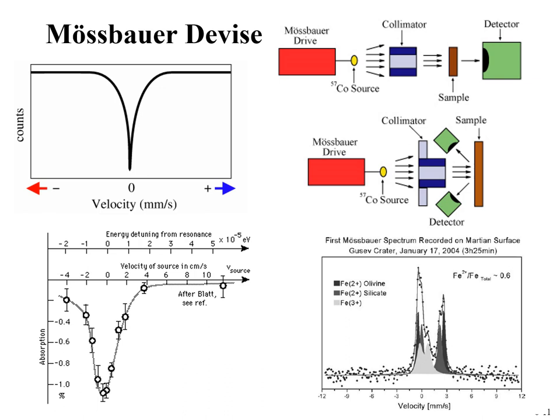The data is shown here. Here's the velocity of the source, the absorption lines. What one can do is look at these chemical shifts, and you can get an idea of what iron components are present. And this was important for looking at the total amount of iron 2 relative to total iron. And this gave an idea of oxidation on the Martian surface, which would give an idea about the presence of water.